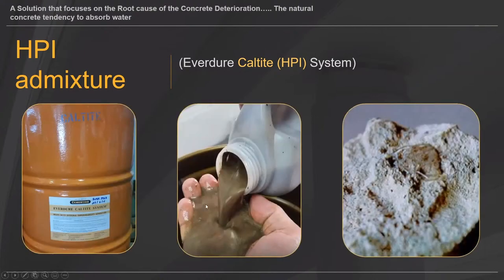So basically, yes, it's a thick brown liquid which is added to concrete. It has two major effects. One is to block all of the pores and capillaries, and the other is to render all of those pores and capillaries hydrophobic or water repellent. You can see this photograph on the right here. This is the effect of putting a droplet of water onto the top of HPI concrete. It just beads up and sits up on top. It's almost as if there's a wax coating on there. It just will not get absorbed into the concrete.